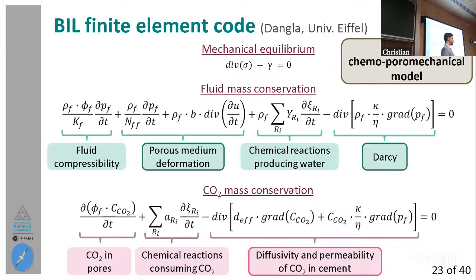This is a fully coupled chemo-poro-mechanical model, which solves these 3 equations. We have first mechanical equilibrium, then we have a fluid mass conservation, which is mainly the conservation of water, from which I'm going to focus particularly on the porous medium deformation, which depends on the elastic parameters of the porous material, which is the cement matrix. That will be affected by the estimation of the elastic parameters in the compound material. And then we have the Darcy term, which is related to permeability, which will be affected by the rupture of the spheres due to the increased internal porosity.